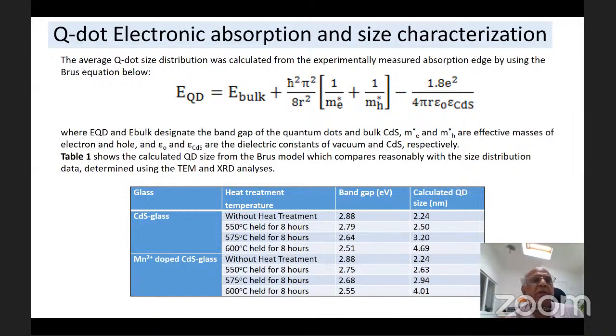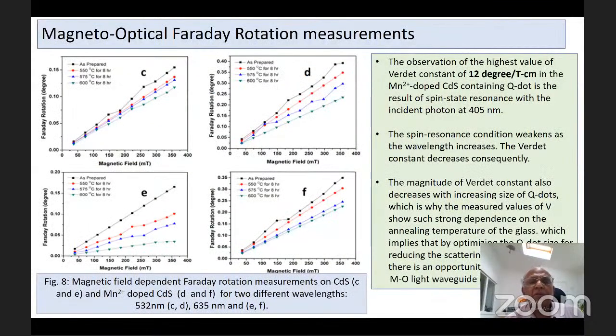and Mn-doped CdS glass. We then went on to measure the Faraday constant by calculating the Faraday rotation as discussed before, and what we found was that the highest value of the Faraday constant was 12 degrees per Tesla centimeter in Mn-doped CdS containing quantum dot glass, and this is resulting from the spin state resonance of the incident photon at around 405 nanometer, which is where the band gap of the CdS glass usually is. The spin resonance condition weakens as the wavelength increases.